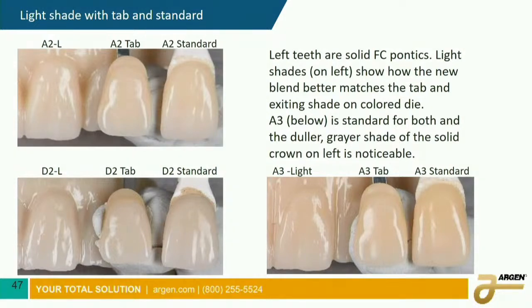And for fairly thick restorations, like those all-on-4, you can see the light shade actually matches the shade guide better than the regular HTML. Even on a D2 or on a darker shade like an A3, the light shades are much better for the long span bridges where you're going to have a large, thick amount of zirconia, like the all-on-4 bridges, as you know.